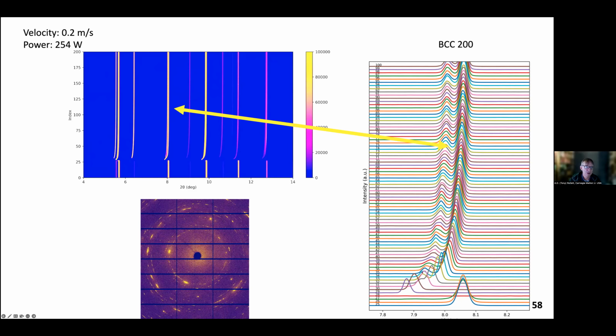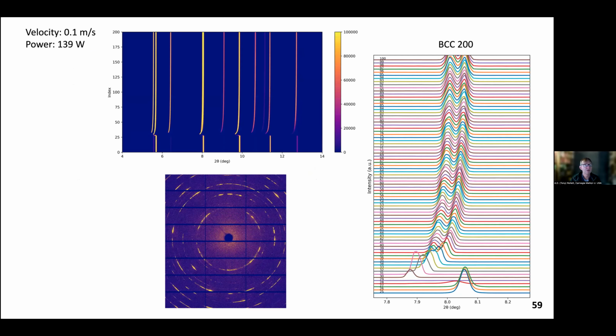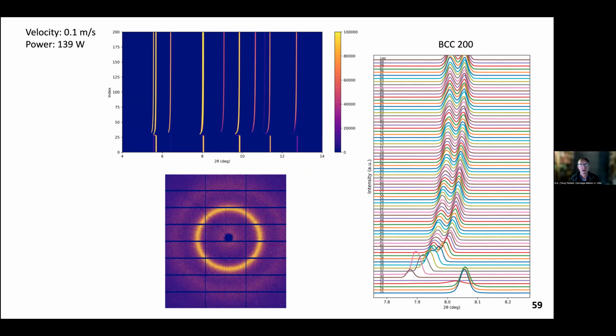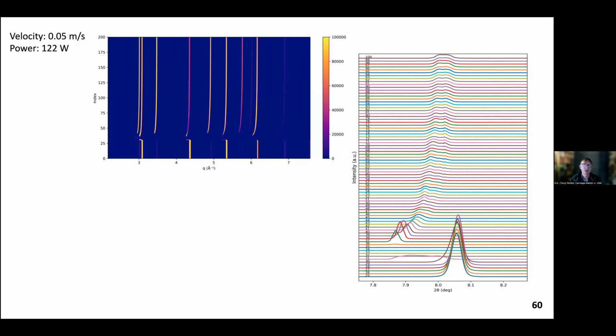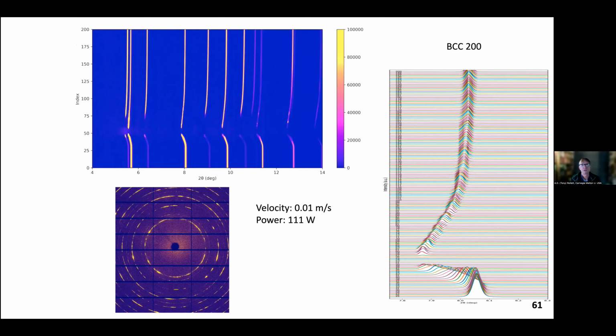Now, I don't have temperature associated with this, but here where the splitting is becoming clear, it's still pretty hot. I mean, it's going to be up around 1000 centigrade or so in that first, second, third, or fourth frame. And as you step through a slightly slower cooling rate, the splitting is still obvious almost from the get-go. But as you slow down, then the split is still there, but it's just somewhat less obvious. And then if you go slowly enough, it really isn't there.